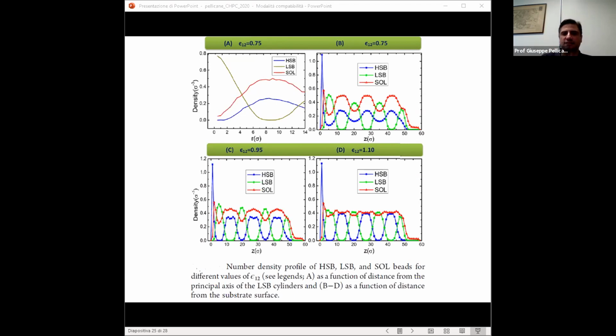The density profiles as a function of the distance from the interface are shown again in panels B and D. They are very informative in explaining how the phase transition from cylindrical to lamellar morphology takes place as the solvent quality changes from poor to good. Our conclusion is that as the quality of solvent increases, the cylindrical morphology at those peak locations deforms into elliptic cylinders with the larger radius parallel to the substrate, and finally evolves to a lamellar morphology in a good solvent.